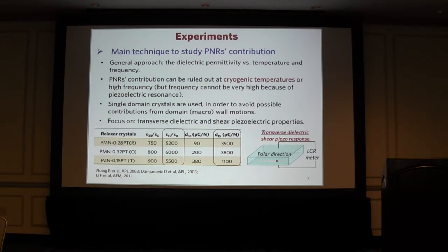In order to study the polar nanoregions contribution, the general approach is to study the dielectric permittivity with respect to the temperature and the frequency. Because the polar nanoregions contribution could be ruled out at cryogenic temperature or very high frequency. But as you know, the relaxor-ferroelectric crystal has very high piezoelectric response, so the measured frequency cannot be very high for this crystal because of the piezoelectric resonance. So our study focuses on the transverse dielectric and shear piezoelectric properties of relaxor-ferroelectric crystal.